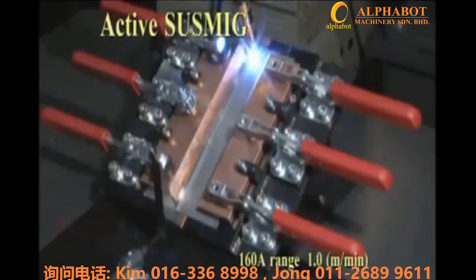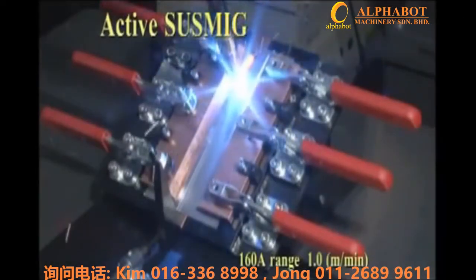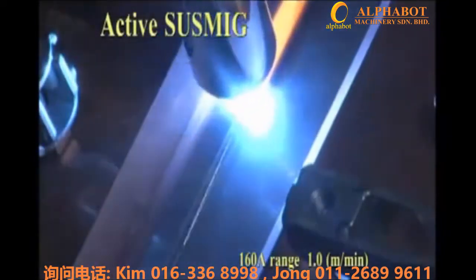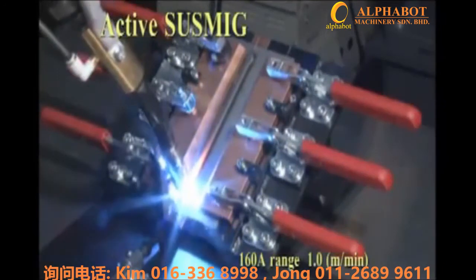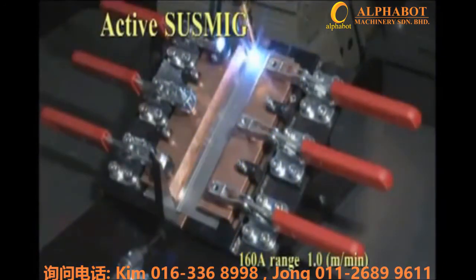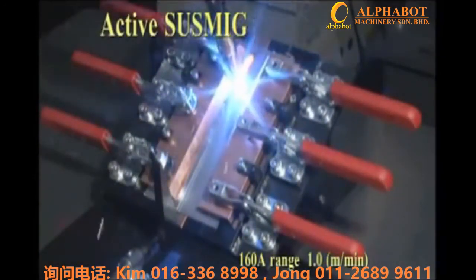The demonstration is a 3-layer joint of 0.5, 0.5, 1.0 millimeter material with a 0.5 millimeter gap introduced between the second and third layer. Conventional processes have two typical issues: insufficient penetration to the top edge, or burn through of the bottom plate.